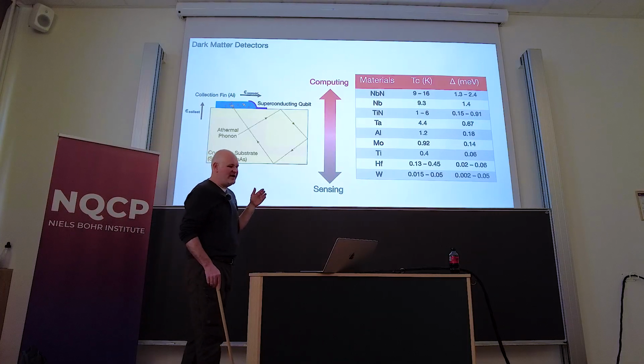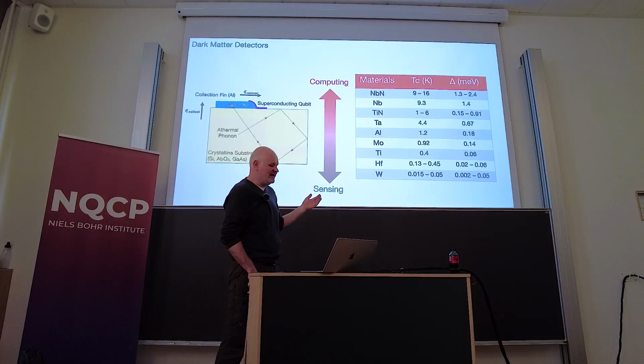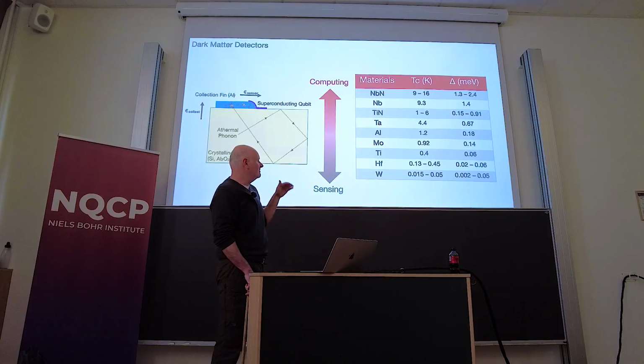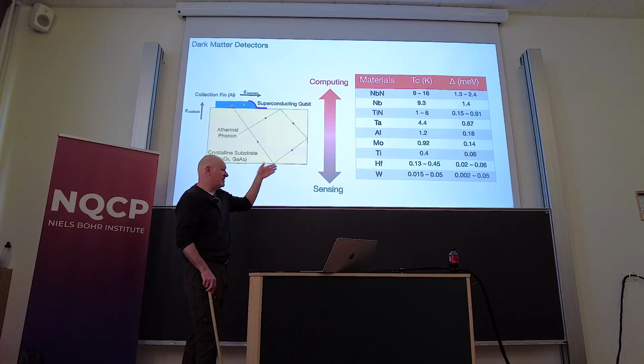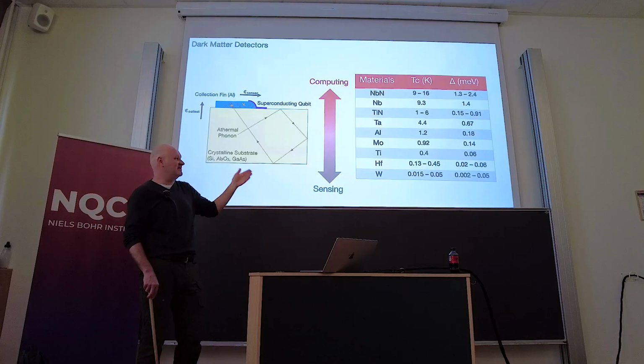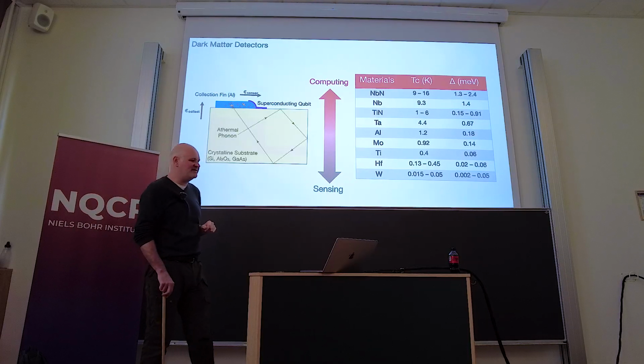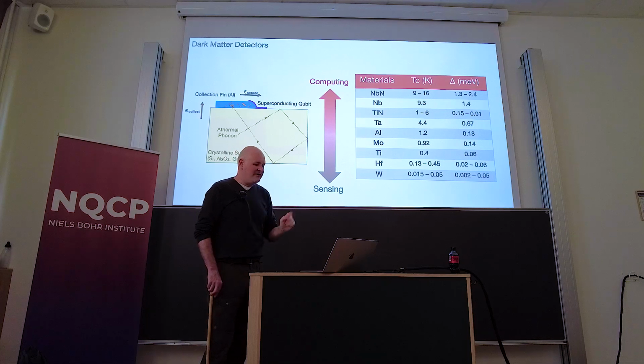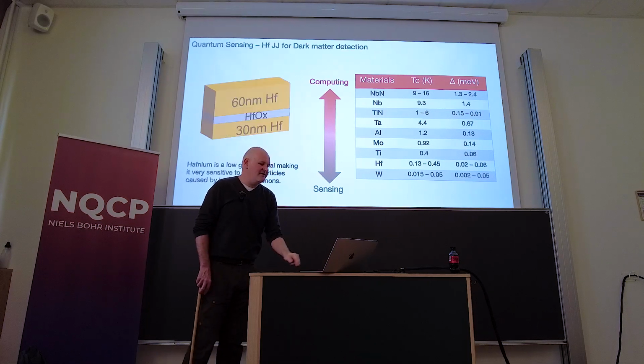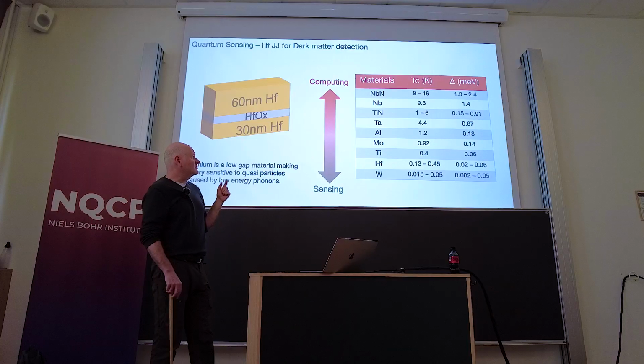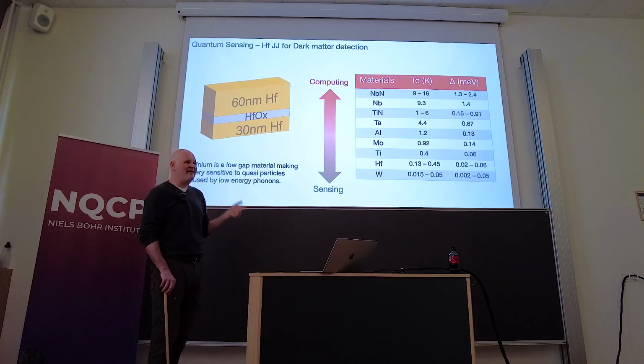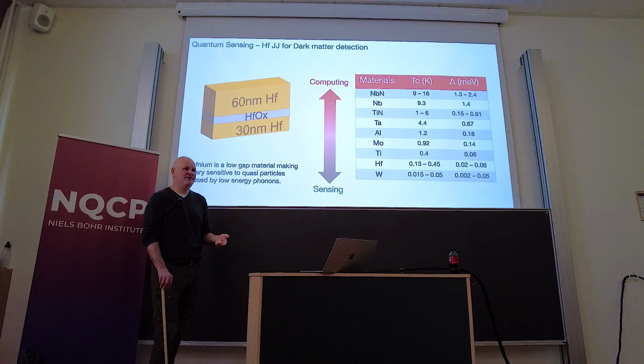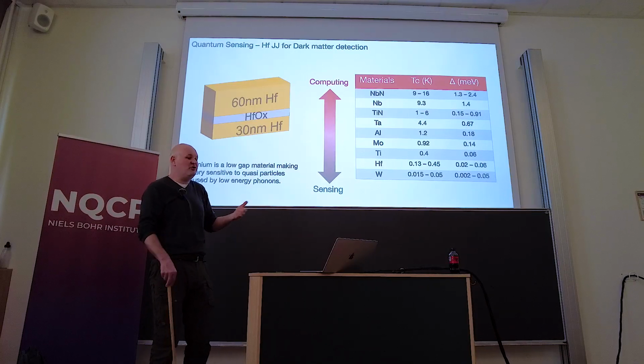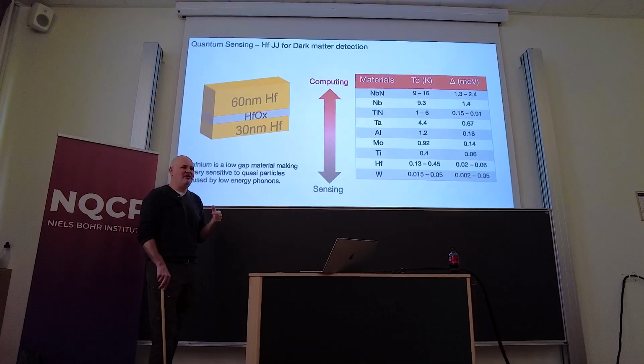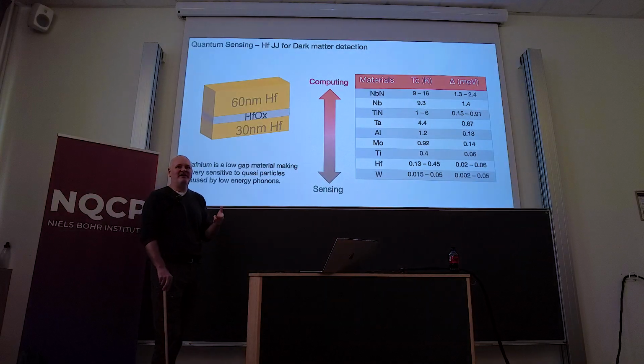And so what we decided to do was, tungsten is the material that's used for the transition edge sensors because it is the lowest TC that you can achieve for this particular phase. But hafnium is a close second. And we decided to try and make essentially a hafnium Josephson junction to make a full hafnium qubit. And again, it's a bad qubit. You don't want it to be a good qubit. What you want it to be is very, very sensitive and very lossy.